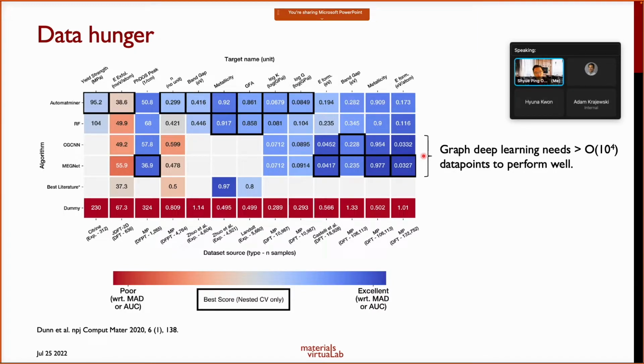Now, the second way in which you can handle the data scarcity issue is using the MEGNet model as an encoder, right? So this is actually not work from my group. This is work that was done by the group of Anubhav Jain, where he basically benchmarked a lot of different machine learning models, including MEGNet, on various data set sizes. So things like the yield strength, the exfoliation energies, they also have the band gap data, as well as the formation energies, right? So what you will notice immediately from this plot is that when the data set sizes are very small, especially when it's below 10,000, so things like, for example, the yield strength or the exfoliation energies, the best models are never the MEGNet or the graph deep learning models, right? It is usually some random forest type model or the AutoMatMiner algorithm, which basically generates an ensemble learning model.